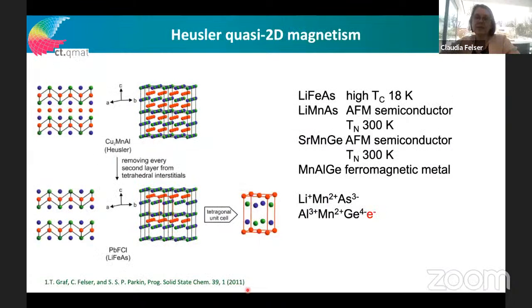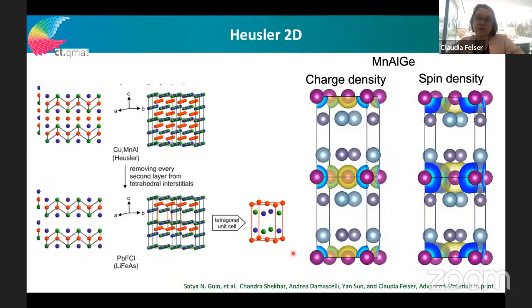Okay, so I am coming to the end, only a few words. We try to make more two-dimensional materials. We try to make Heuslers also two-dimensional, and this you can do if you go to the quasi-relatives of Heusler. This is a structure type called PbFCl. It's related to LiFeAs, which is a superconductor. So we could find a material which has a more two-dimensional magnetic structure, and this is manganese aluminium germanium. And to make a long story short, we find everything we expect there.